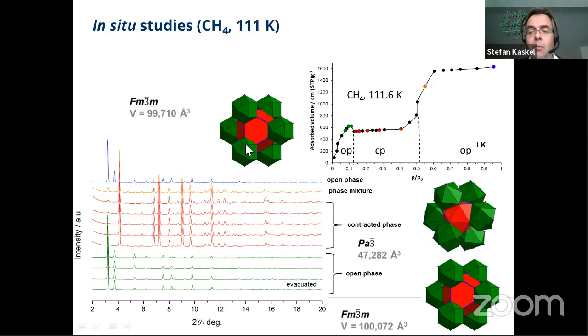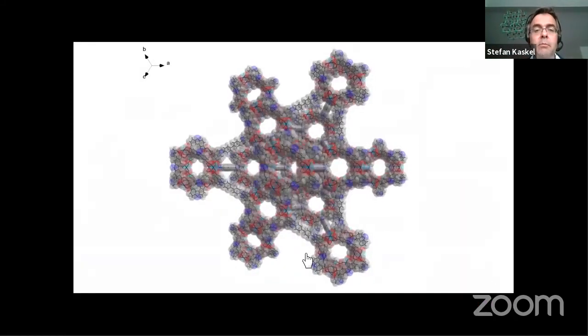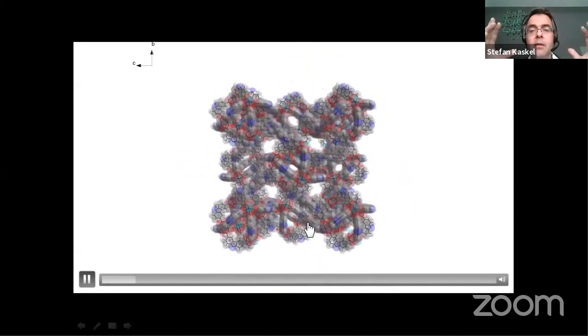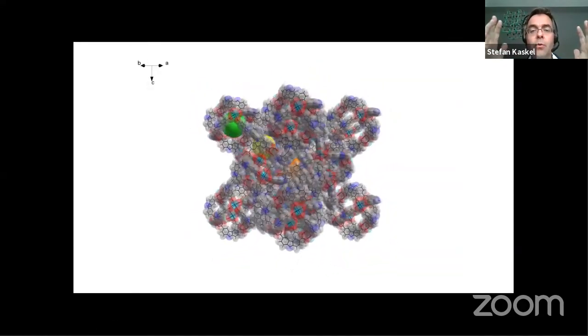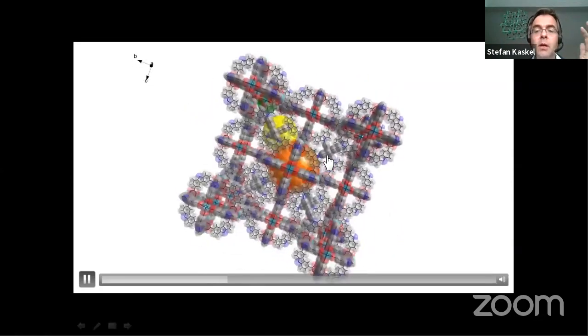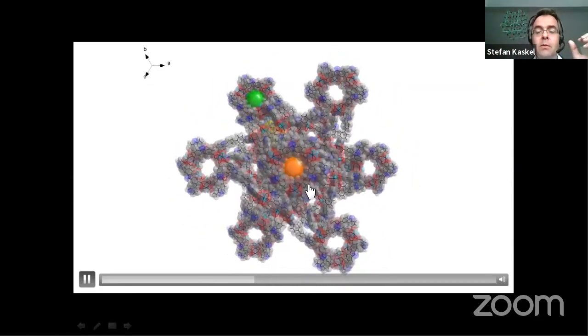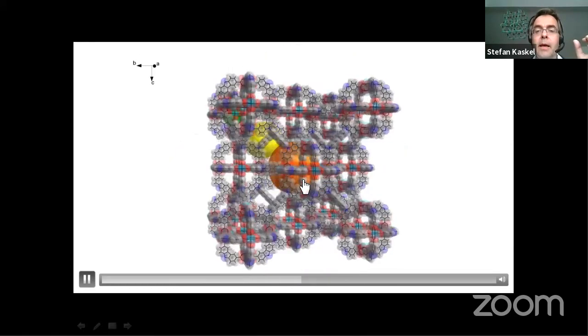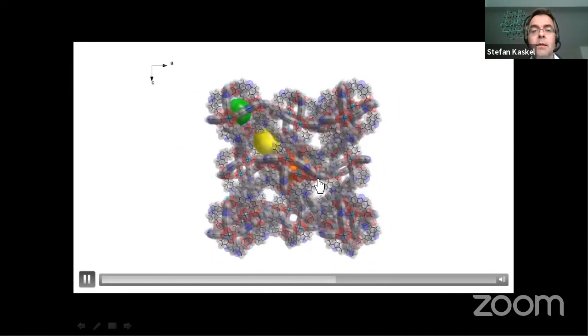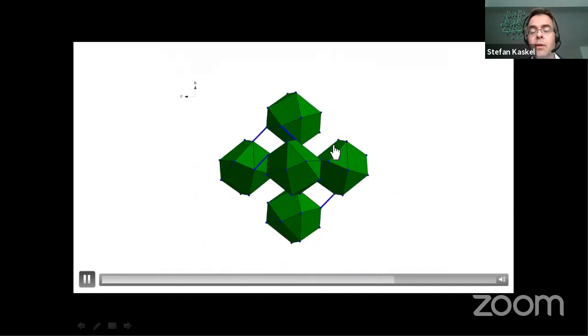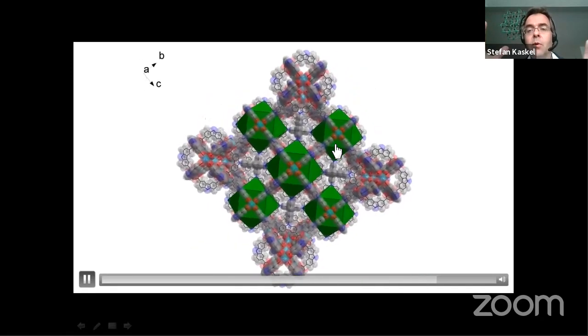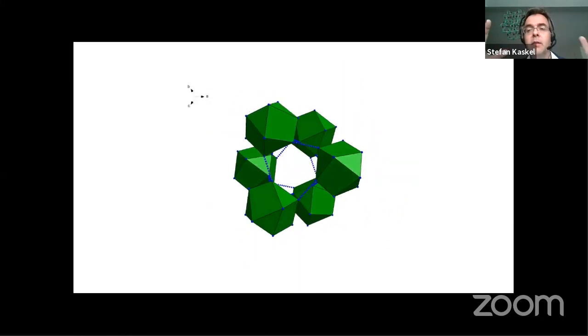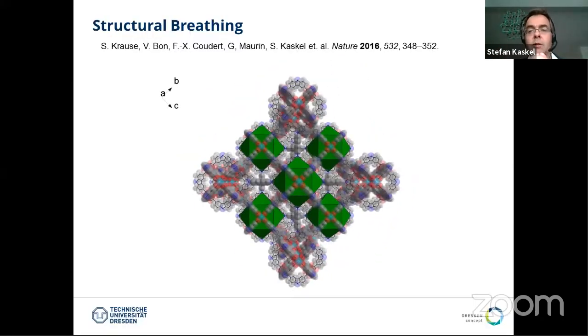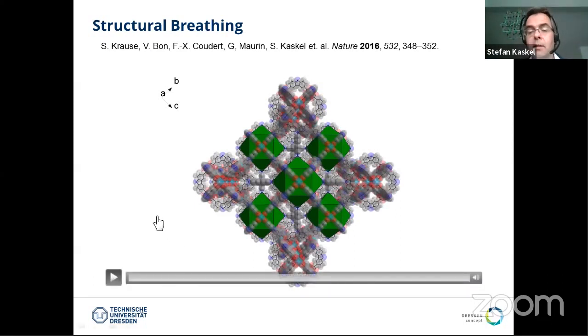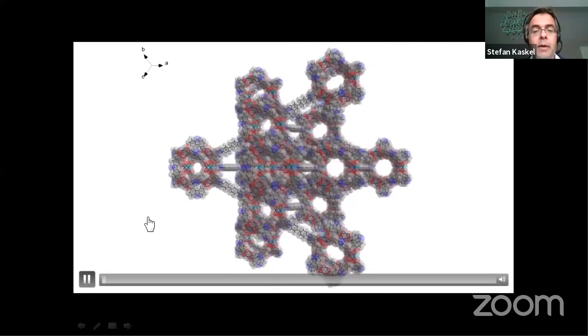So this is a breathing MOF. You can see this in the following animation, basically, that the intermediate phase contracts the mesopore of 2.4 nanometer, this orange pore here, to a micropore of less than 1 nanometer, 0.9 nanometer. And then it reopens again at higher pressure. It's a breathing mesoporous MOF essentially. And the reason for the negative gas adsorption is basically that in this spontaneous contraction, the gas, the methane, is pushed out and expelled basically to the cell, causing a pressure amplification.